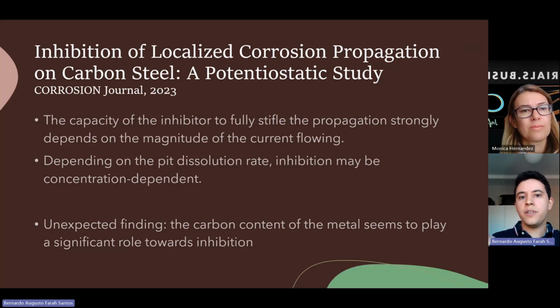So we observed that there will be a threshold in which the current will be too high. It will be higher than the adsorption mechanism of the inhibitor to the surface. So the inhibitor has a limit when it's facing a high dissolution rate. That's usually what's happening in the pit.